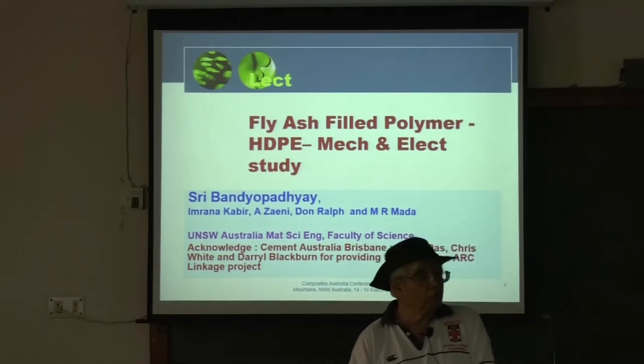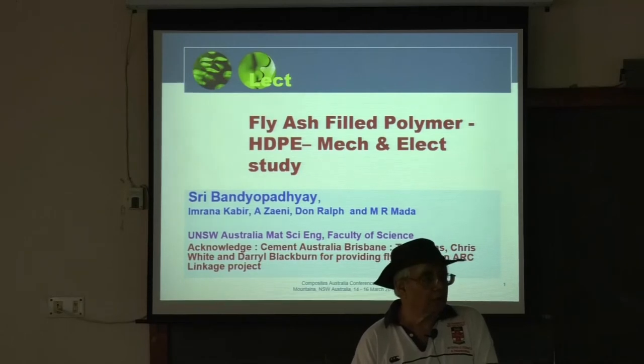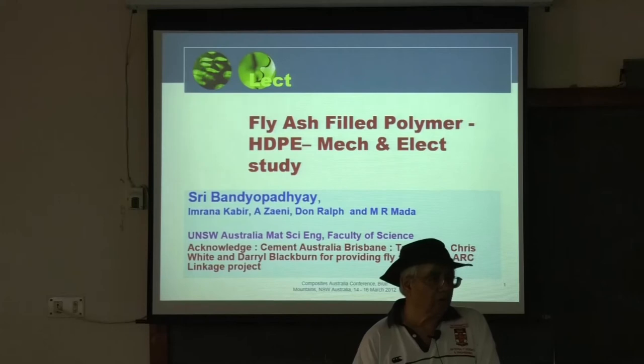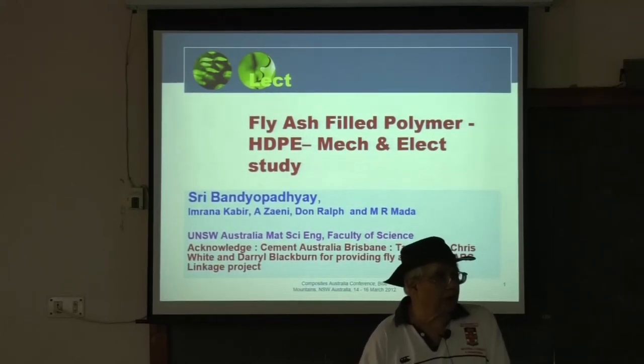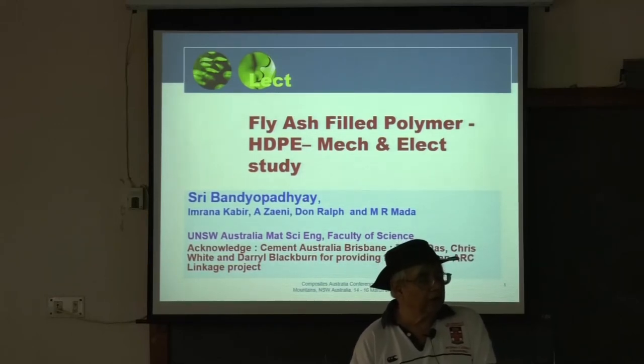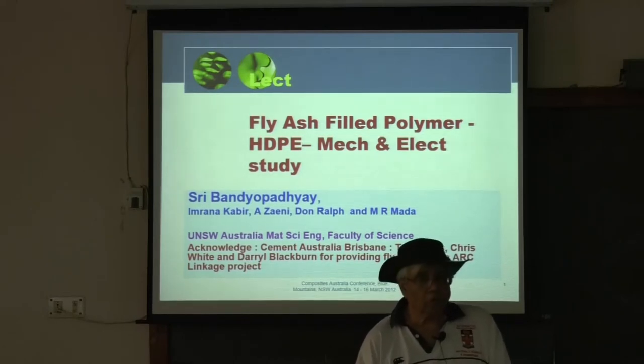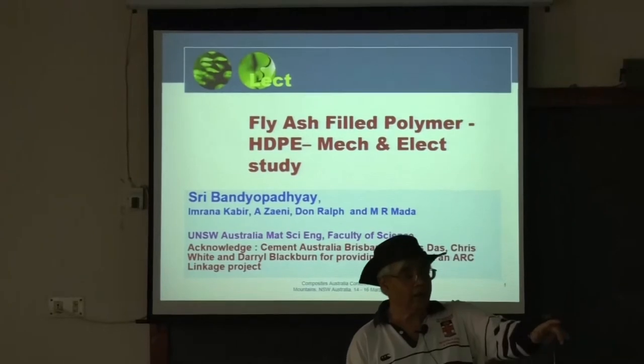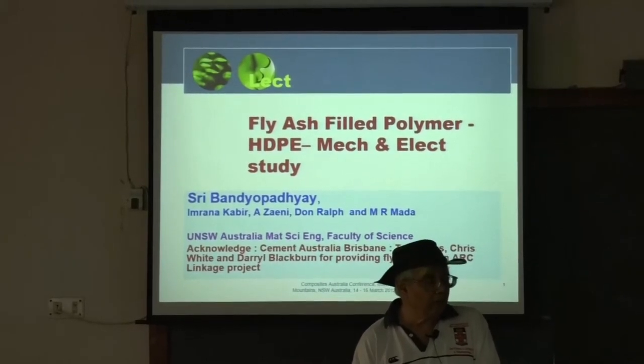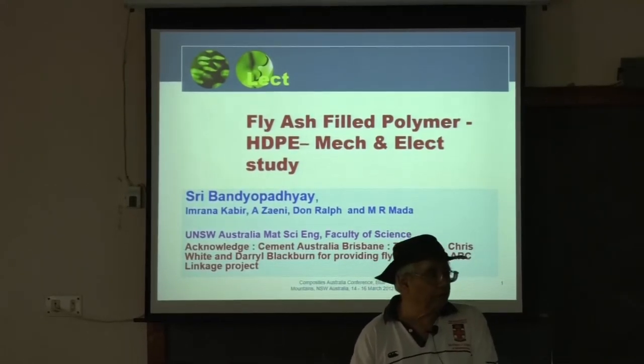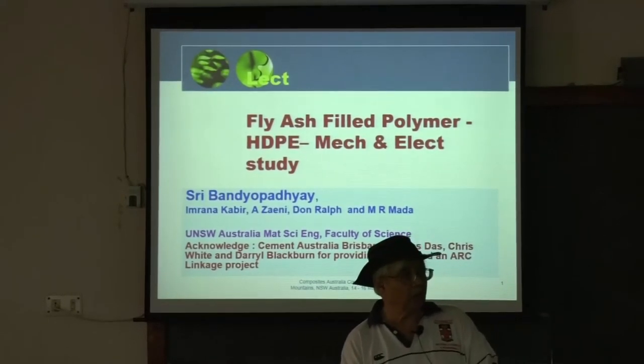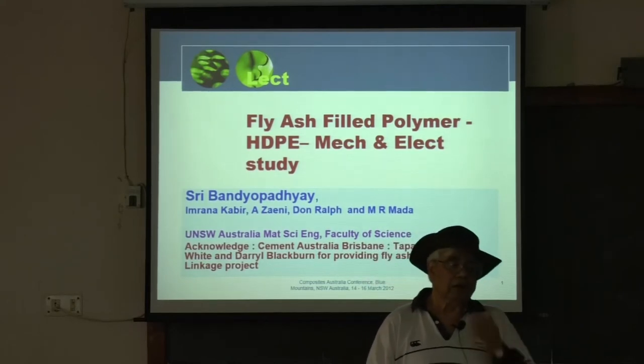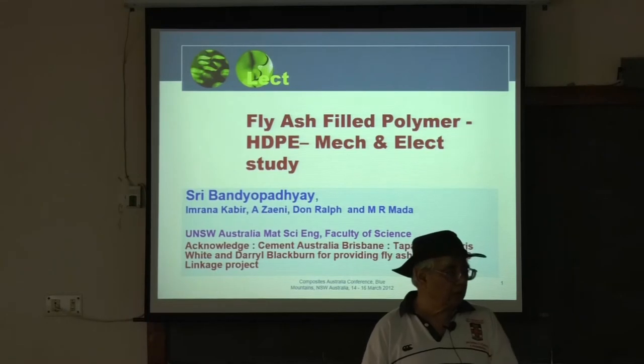So far in these lectures, people have done characterization of mechanical properties, fracture properties, impact properties, bonding properties by FTIR, and lots of other things. But as I mentioned, fly ash can also improve the electrical properties in polymers and plastics. Can you tell me which component of fly ash can improve the electrical property? The answer is LOI — loss on ignition — because LOI contains the residual carbon, whereas all the ceramic components are insulators.